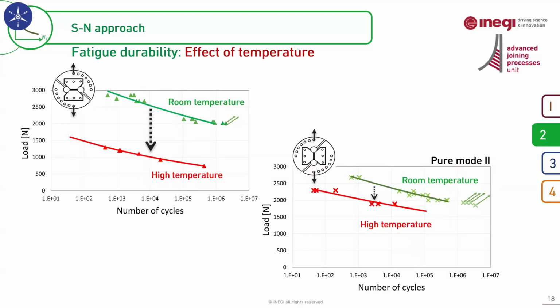One of them is the effect of temperature. When we tested the joints under high temperature, we noticed that the sensitivity of mode 1 to high temperature is much higher than mode 2. This finding reinforced again the importance of designing joints in a way to be loaded mainly in shear.